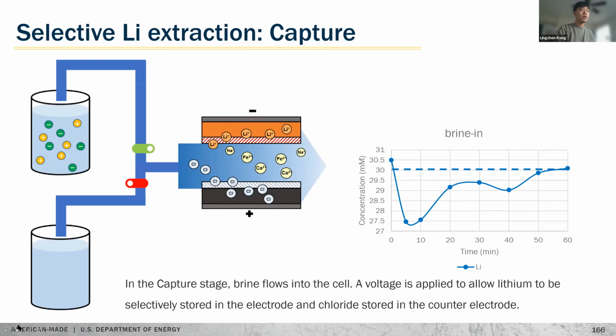Next slide, please. This is the demonstration of how we capture the lithium from the brine. We have a continuous setup, and in this capture process, the brine will feed into the cell and the pure water channel will be closed. Then we apply a voltage, and the lithium will intercalate into the lithium intercalation material. The right figure shows that we only use milligram scale of active electrode material, and we can achieve lithium selective extraction within tens of minutes.